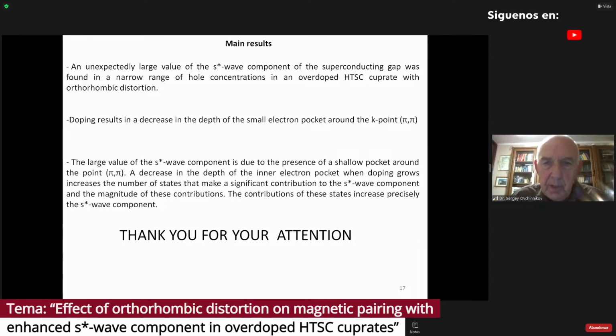A decrease in the depth of the inner electron pocket when doping is growing increases the number of states that make a significant contribution to the S-wave component and the magnitude of this contribution. So the contribution of the states increases precisely the S-wave component. That's all. Thank you for your attention.